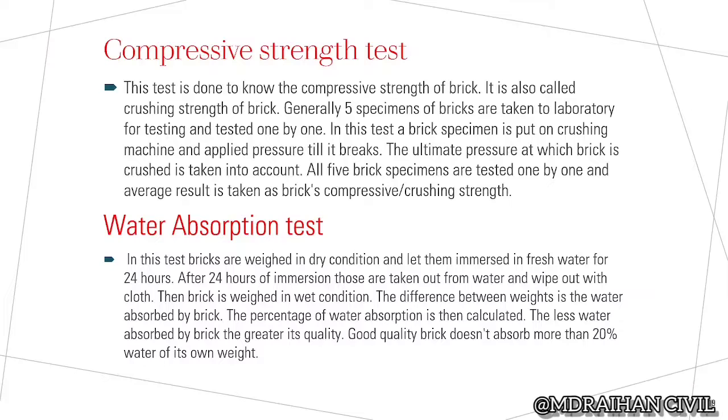In this test, a brick specimen is put on a crushing machine and pressure is applied till it breaks. The ultimate pressure at which the brick is crushed is taken into account. All 5 brick specimens are tested one by one and the average result is taken as the brick's compressive or crushing strength.